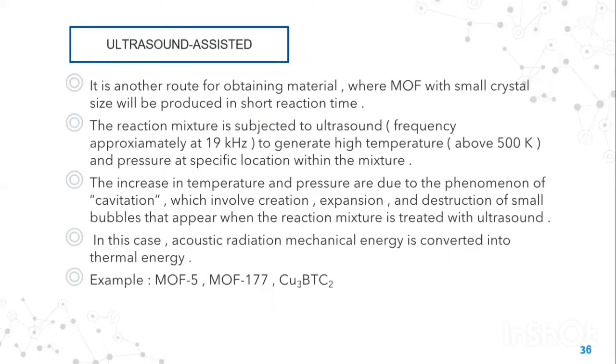Ultrasound-assisted synthesis is another route for obtaining material, where MOF with small crystal size is produced in a short reaction time. The reaction mixture is subjected to ultrasound of approximately 19 kHz to generate high temperature above 500 K and pressure at specific locations within the mixture. The increase in temperature and pressure is due to the phenomenon of cavitation, which involves the creation, expansion, and destruction of small bubbles that appear when the reaction mixture is treated with ultrasound.